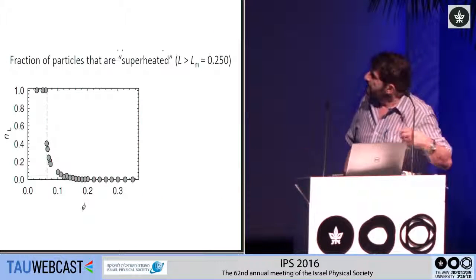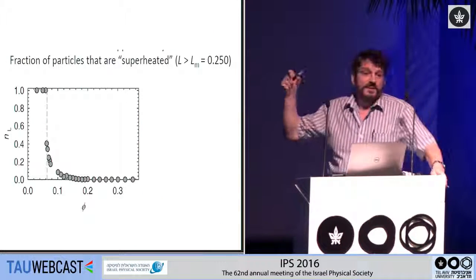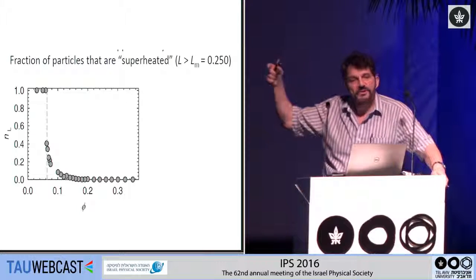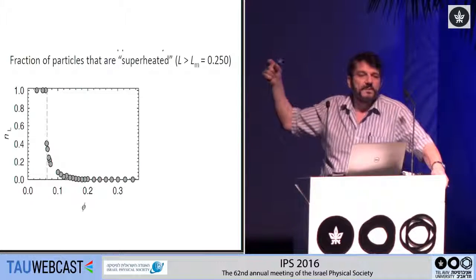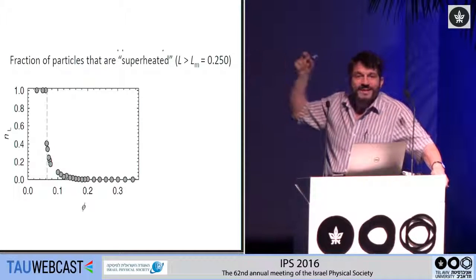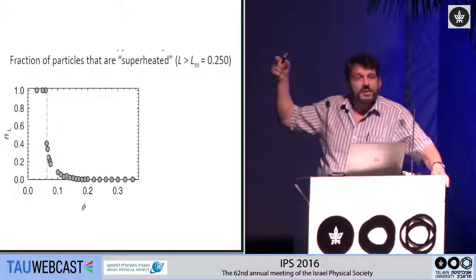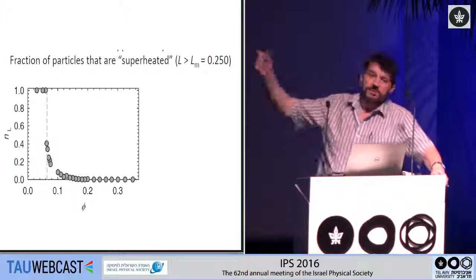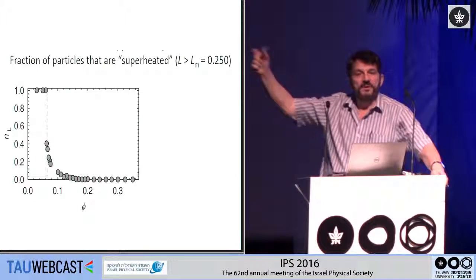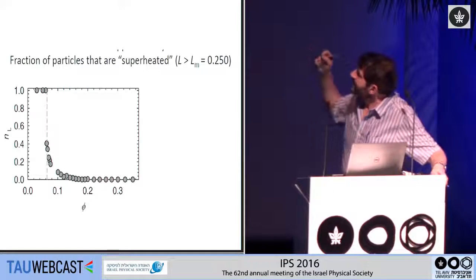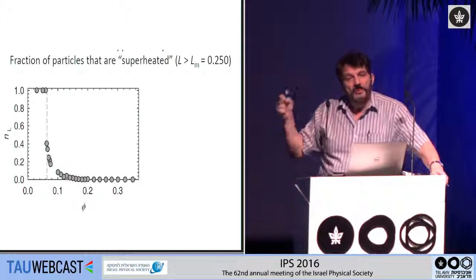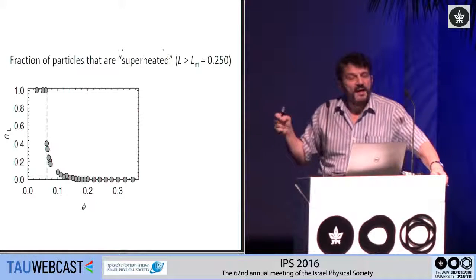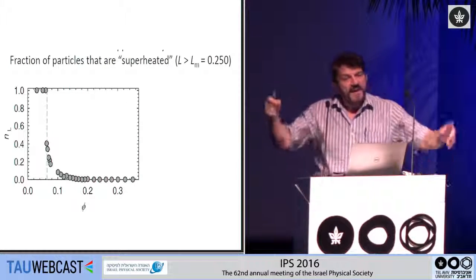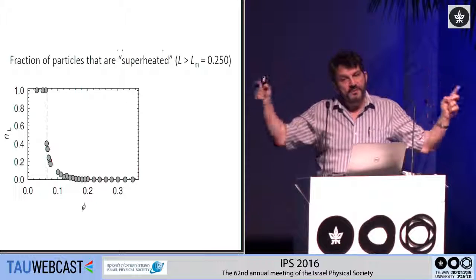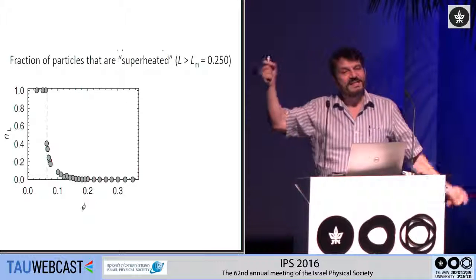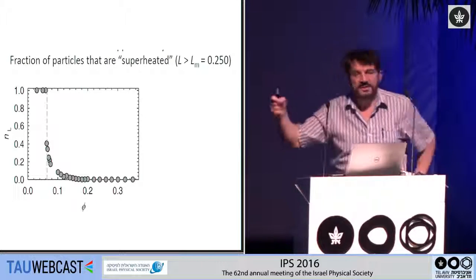And you can say, well, okay, look, the average Lindemann criterion at melting is something like 0.25. But you can look at the individual particles and ask, what are their Lindemann parameters? You just measure the fluctuation for some period of time of each of the particles, and you find that some of the particles have Lindemann parameters that are much larger than that of the melting value. They have these enormous fluctuations. And remember, they have these enormous fluctuations, but they still retain their positions on the crystalline lattice.